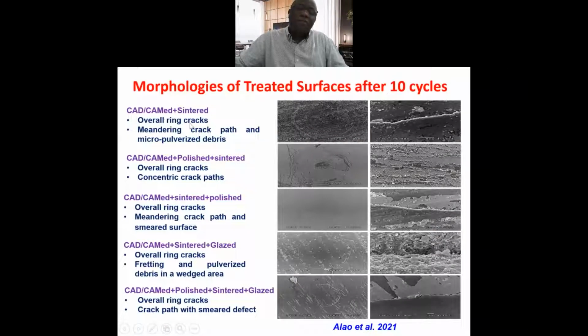So you can see overall ring cracks. You can see the meandering crack path and the micro pulverized debris. For the CAD-CAM polished sintered, you can see overall ring cracks, and you can see the concentric. Now this one has changed from the ring cracks to the concentric crack path. For the CAD-CAM sintered polish, you can see the ring crack and meandering crack path and smeared surface.